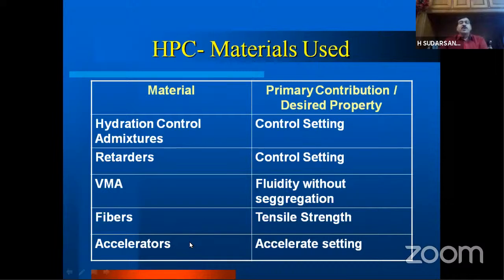Then we have hydration control admixtures, retarders to control the setting, viscosity modifying agents to obtain the fluidity without segregation. As we know, segregation can damage the quality of the concrete. So we use VMA, the viscosity modifying agent. We have different types of fibers to improve the tensile strength of the concrete, where the concrete has to have a good tensile strength. Accelerators, if you want to have a quick setting.